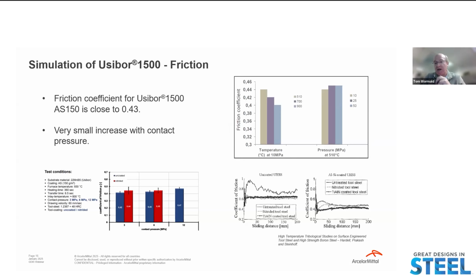Preferences certainly exist by user, established through their own experience in correlation to stamping results, usually involving blank movement and thinning. ArcelorMittal has tended to find increased accuracy with somewhat lower friction values within that range, but it's especially challenging to identify a single value for friction with all the variables that exist in the hot stamping process.